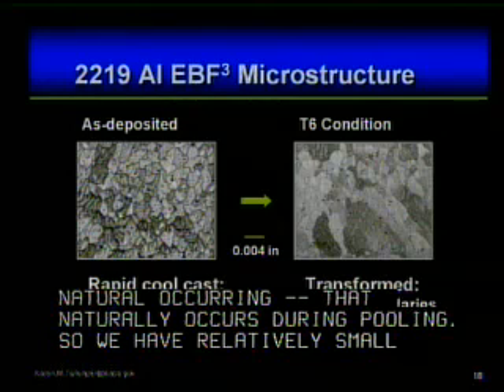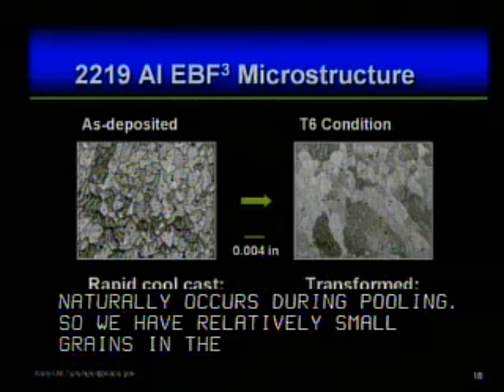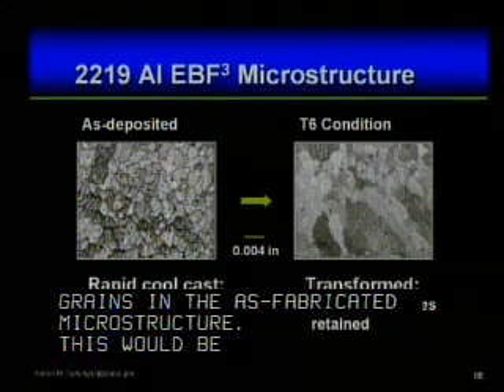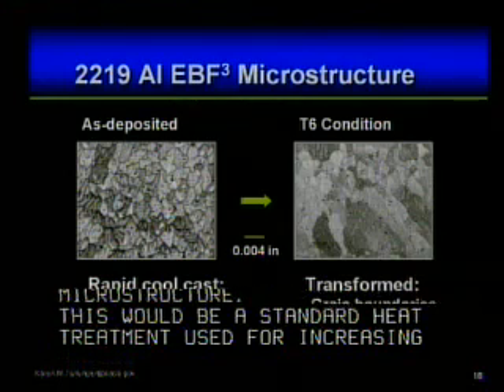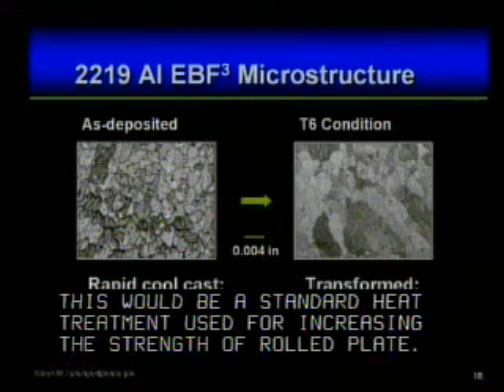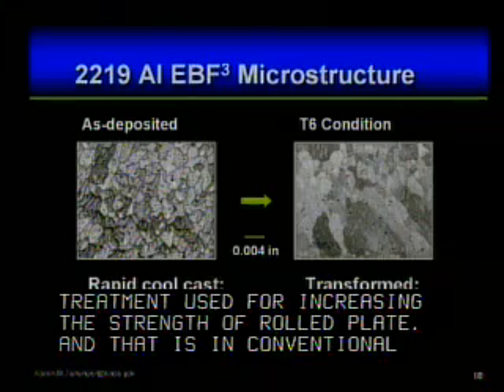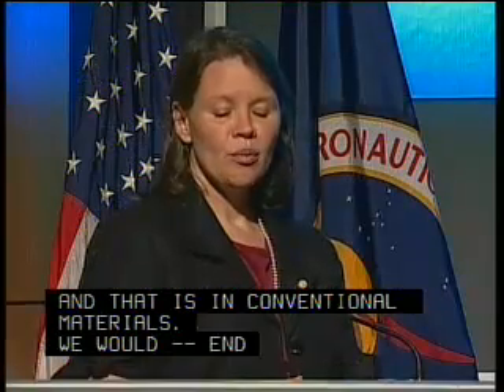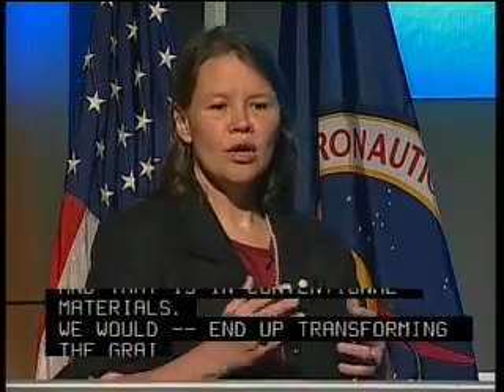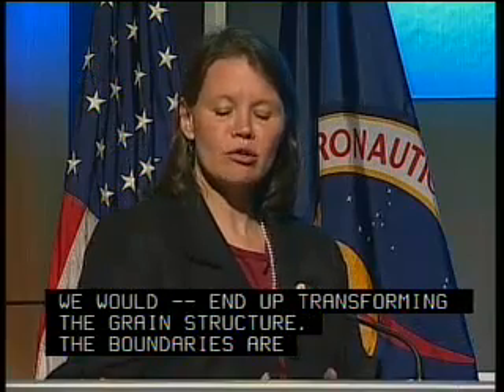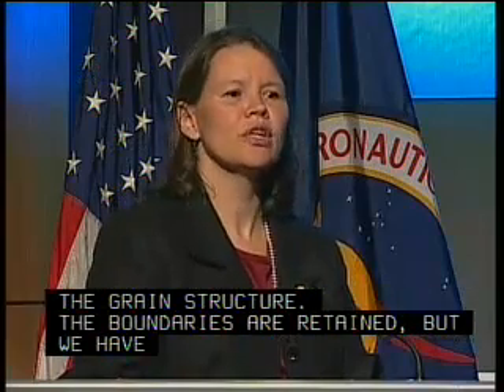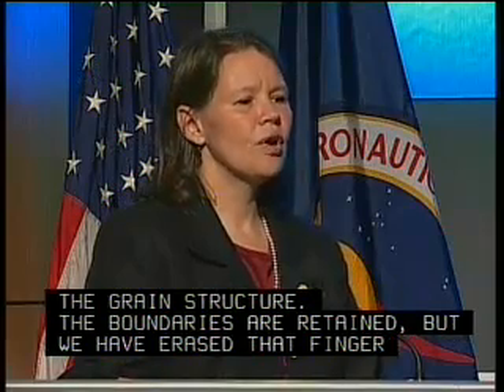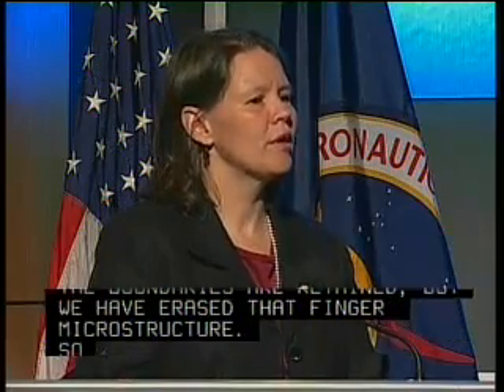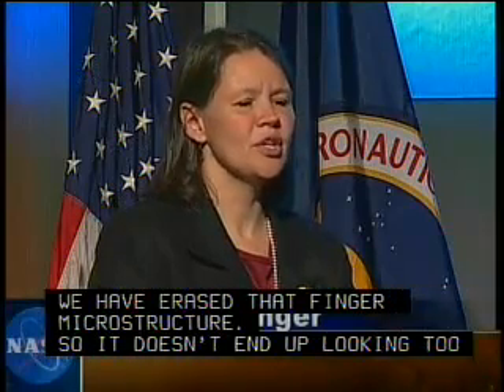Now, if we go through a T6 heat treatment, this would be a standard heat treatment that would be used for increasing the strength of rolled plate in conventional materials. We end up transforming the grain structure, so the grain boundaries are retained, but we've erased, if you will, that finger microstructure. So our microstructure doesn't end up looking too much differently from a forged type microstructure. It's a little bit different, but not too much different.